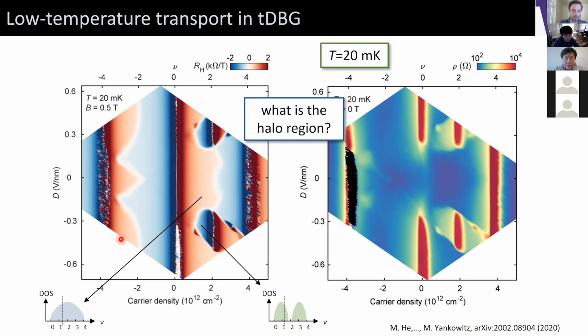So if we imagine that the chemical potential is just slightly under half filling, that means that we're just below a Van Hove singularity in the parent fourfold degenerate band. So we would be measuring electrons. But if the band is spontaneously symmetry broken, now we could be in a condition where we're measuring holes, even though the system in a single particle model wanted to be electrons. So that's a basic understanding of why the sign would flip. And to get a better handle on this, I want to measure this now as a function of temperature and see how this symmetry breaking evolves.